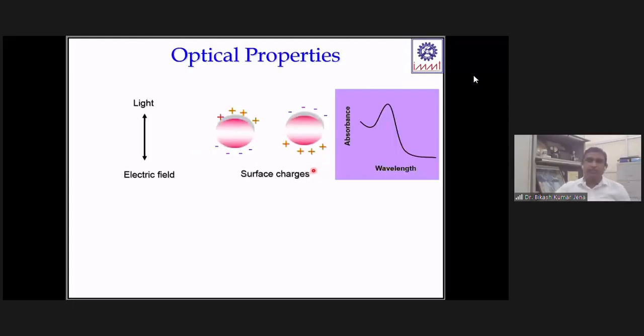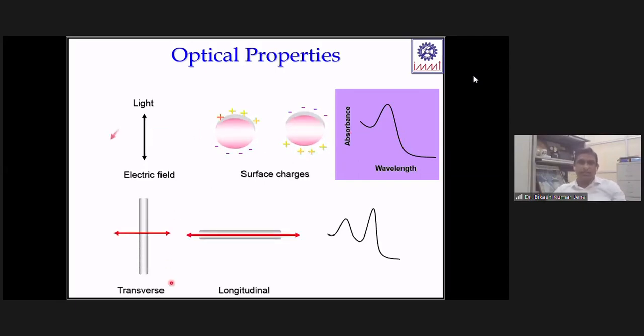So here, what you see, the nanoparticle has a very interesting optical property. This is the gold nanoparticle. When light interacts with the gold nanoparticle, the surface charge gets polarized. That is reflected as an absorbance. A 10 to 15 nanometer gold nanoparticle shows absorbance at around 515 to 520 nanometer wavelength. It will change as you tune the size of the nanoparticle.